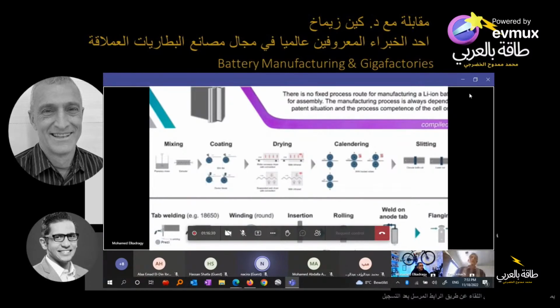So in a dry room, well, you can define it how you want. In general, the industry standard for a dry room for manufacturing lithium-ion cells is something that has a dew point, and I'll get to defining that, at the dry room temperature of minus 40 C. Meaning at 40 degrees below, if you had a surface in that dry room that was at minus 42 degrees centigrade, water would condense on that out of the air.